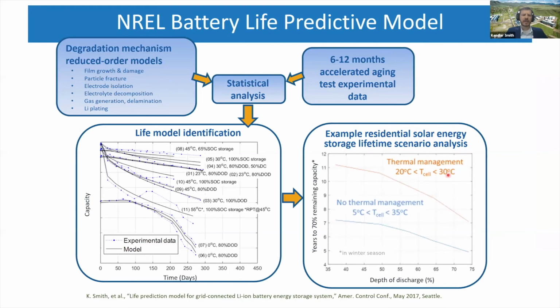So with that, we collect about, like I mentioned, 6 months of accelerated aging data, go through a procedure to identify the model at different temperatures, have Arrhenius formulas to map out the rates of fade versus temperature, Tafel equations to map out the rate of fade versus different states of charge or negative electrode or positive electrode equilibrium potentials, and some empirical expressions like power law to describe depth of discharge and C rate. And with that, you can have a model that runs complex scenarios as well.